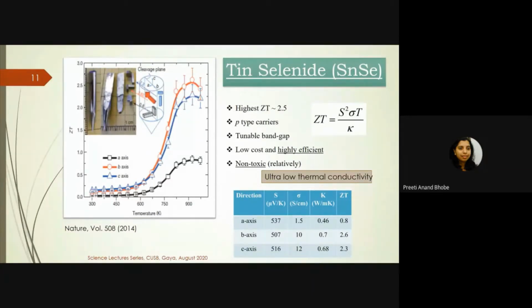The scientists who reported this, the US group in 2014, claimed they made single crystals, as shown in this photograph here. They made single crystals of this material, and they showed that the single crystals were anisotropic. The properties of the material were not isotropic along the different a, b, c axes of this material. You were getting different electrical and thermal conductivities.